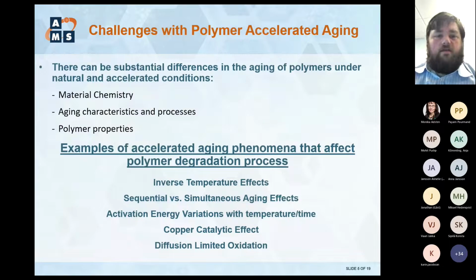So again, and it was mentioned in the previous presentation, you have to take the accelerated aging data, its relationship to in-service conditions, with a grain of salt, because there can be substantial differences depending on your aging condition and the type of material you're dealing with and the cable. There can be substantial differences in what happens under accelerated aging conditions and what happens to the material under natural aging conditions. There can be differences in material chemistry. There can be differences in aging characteristics and processes, and in turn, because of all these kinetic differences and reaction mechanism differences, the polymer can potentially have different characteristics and properties.